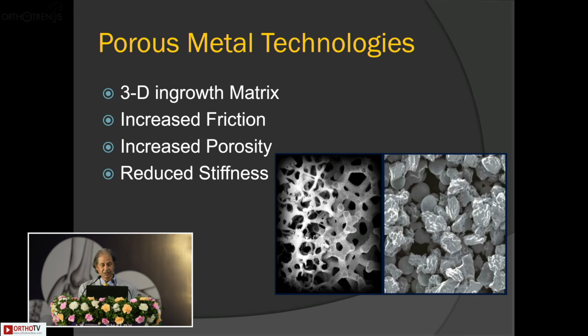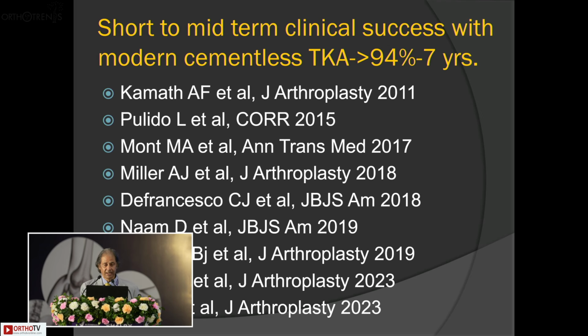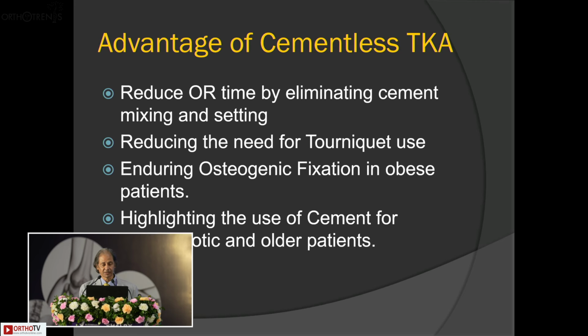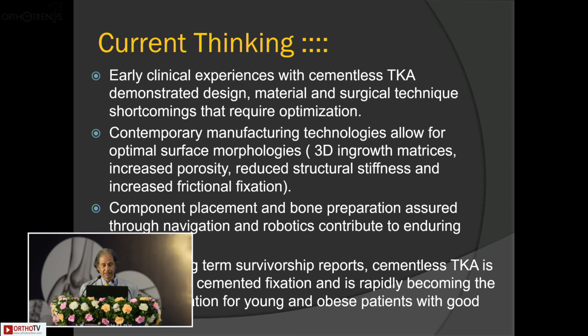The 3D matrix increased friction, increased porosity, and reduced stiffness, and these are porous metal technologies like the TM and tantalum. And again, at midterm, it's 94%. At 7 years, several authors have reported this in literature. The advantages being that it eliminates the cement issues, reduces time for tourniquets, and it really works quite well in most patients. This is the real current iteration.